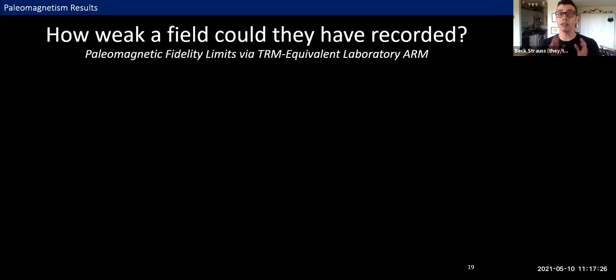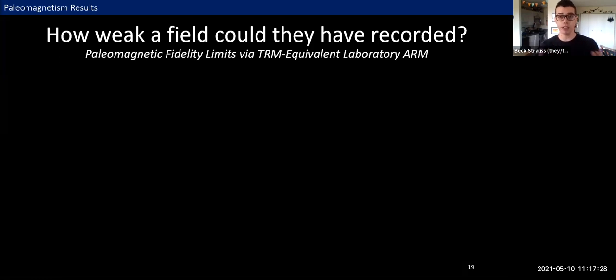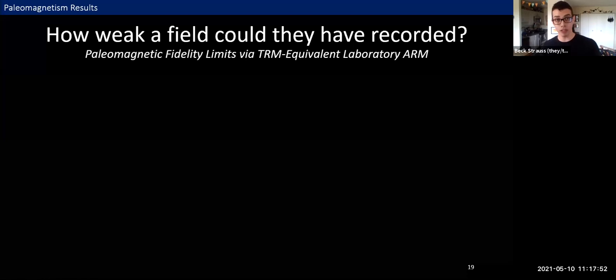Now, to determine fidelity limits for these three samples, essentially determine how weak a field they could have picked up, we performed a series of laboratory experiments in which we essentially applied a magnetic field of a known intensity to each sample to simulate the process that it went through on the moon, and then attempted to get back a record of that applied field using exactly the same techniques that I just showed you, the hope being that we should see a one-to-one relationship between the applied field and the retrieved field.